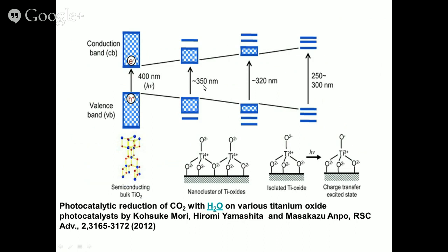From 400 nm the absorbed wavelength becomes 350 nm as we go to larger nano clusters. The band gap is still increasing, and it comes to 320 nm as we go to nano clusters of 40-50 angstroms. When we go to the isolated TiO4, you can see that the band gap has increased further, so the absorbing wavelength is between 250 to 300 nanometers.